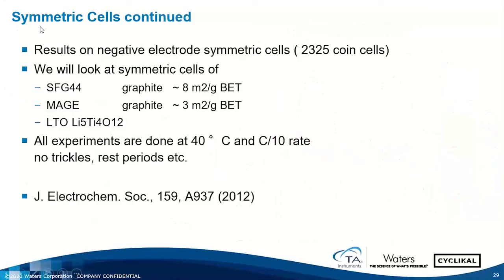All right, symmetric cells continued. So let's look at some integration subtraction methods for characterizing a couple different types of graphite and on the lithium titanate electrode. So we're going to look at symmetric cells of synthetic flake graphite, which has a surface area of 8 square meters per gram. Another graphite, which is considerably lower, 3 square meters per gram. And then the lithium titanate cell. That's a negative electrode, similar to graphite, but with a dramatically different potential.